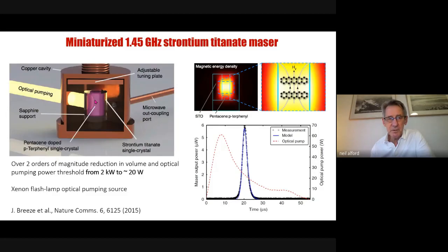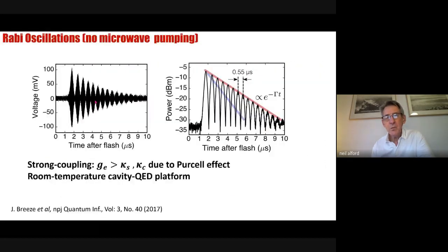You can see we've got optical pumping in a very small copper cavity, and we can see this beautiful result, still using a flash lamp, but the pumping threshold went from 2 kilowatts to 20 watts. So this is certainly moving in the right direction. What we also found when we were doing this was that we were able to observe very, very strong quantum oscillations or Rabi oscillations at room temperature. And so this was a very exciting observation and interesting for all sorts of quantum applications.